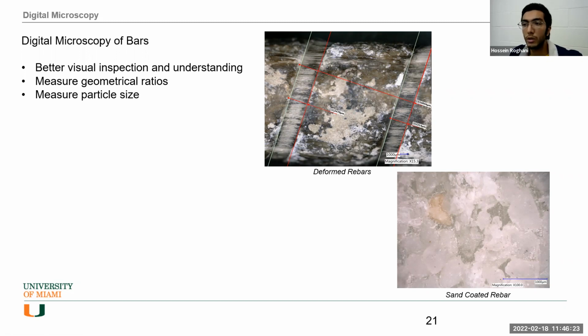So we are trying to use digital microscopes to have a better visual inspection and a better understanding of the surface profile, to really understand what we have on the surface and how the surface changes, from the lug to the flat surface, and also the particle size. In this digital microscope, there are some functions that help you measure your particles, but it is still time consuming. For that we have another approach that I will cover later. But here the digital microscope helps us measure the geometrical ratios that can really affect the bond behavior, which is the main purpose of this study.